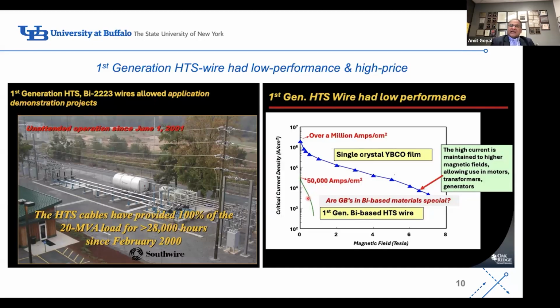In order to realize large-scale applications, what we really need is the blue curve. Here you're plotting the amount of current you can carry per unit cross-section, in amps per centimeter squared. This is over 1 million, starting out at 0 applied magnetic field, and then you apply magnetic field. This is a curve for a single crystal of the superconductor, a film on a single crystal substrate where all the atoms are aligned. The question is, how can we get such a performance in superconducting wires? If we can, then we can potentially enable all these applications, which was the vision that created all this excitement.